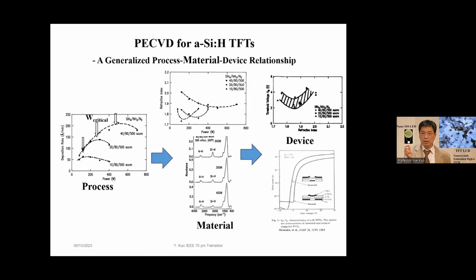The next example is plasma CVD. In this example, in the early stage of production, if you went to 10 companies, they had 10 recipes to deposit thin films, for example the gate dielectric, most commonly silicon nitride. All of them worked, but none of them were similar, and no one knew why, because those came from experimental data. Then we did a publication correlating the process to material to device relationship, and it became clear.